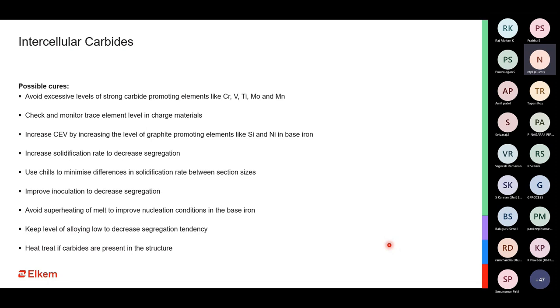We have to, of course, improve inoculation. If that is one of the solutions, we need to use better, high potency inoculants, especially for the critical castings, to make sure that the graphitization potential is improved, and whatever carbon is to come out, it should come out as graphite. We also need to control the superheat. We do not want to heat the metal to such a high temperature that its nucleating potential goes down. And we also have to make sure that we do not cast or melt for a longer time, where the inoculant fades and you have a carbidic tendency. Not something which I'm a fan of.